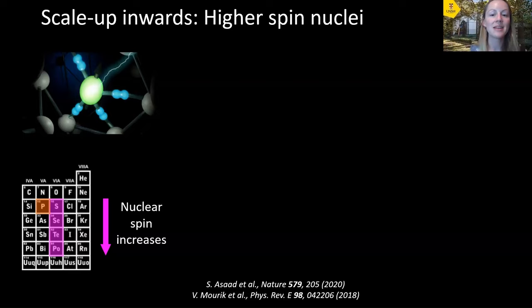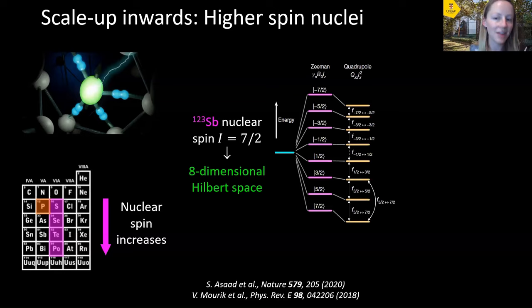So far, I've only been talking about the phosphorus donor. However, there's the whole of the group five donors to explore in the periodic table. And when you go down the group five periodic table, the nuclear spin increases from the phosphorus of just being a boring spin half. You've got the spin up and spin down, which just makes a regular qubit system. But if you move to, for example, antimony 123 isotope, you actually have a nuclear spin of 7 halves, which results in 8 different nuclear energy levels instead of just the spin up, spin down for a nuclear spin of 1 half. And so because all of these energy levels are shifted by the quadrupole moment of the antimony nucleus, it means that they're individually addressable.